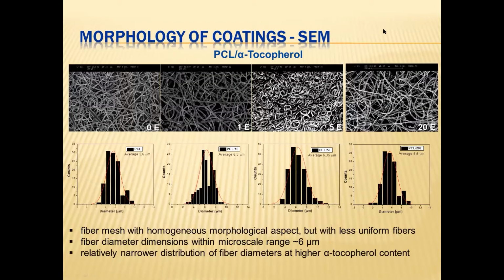The morphology of the fibrous coatings obtained was studied by scanning electron microscopy. The SEM micrographs evidenced a fiber mesh with homogeneous morphological aspect, but with less uniform fibers for the system based on PCL and alpha tocopherol. The fiber dimensions were in the microscale range with an average of 6 microns, and a narrower distribution of the fiber diameters was noticed at a higher tocopherol content.